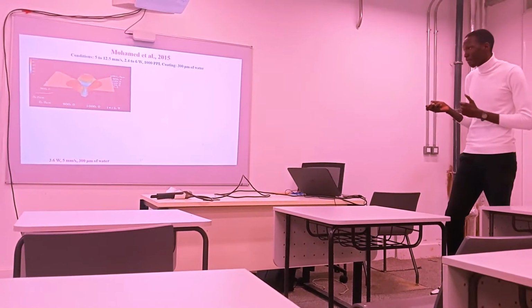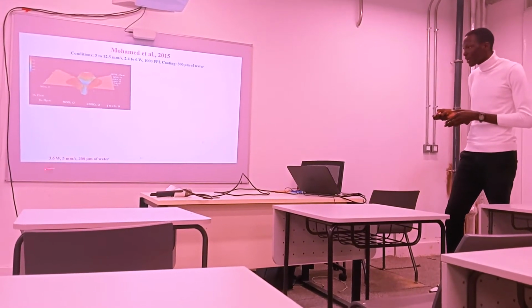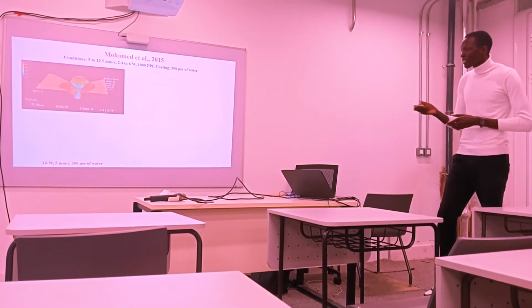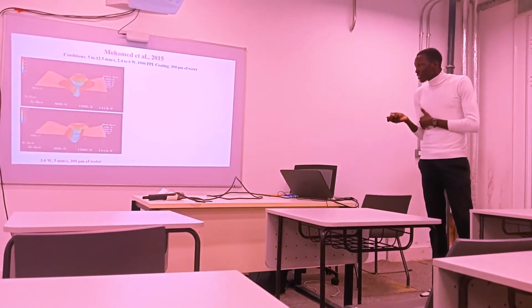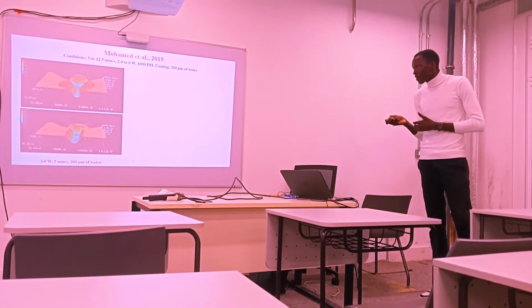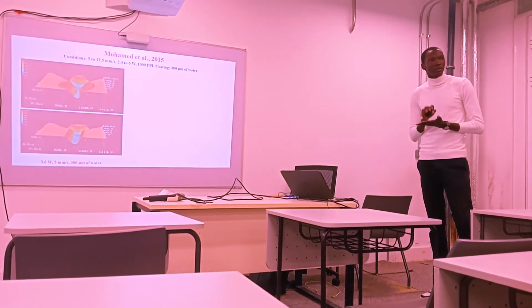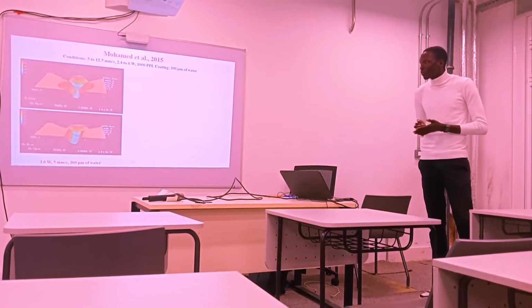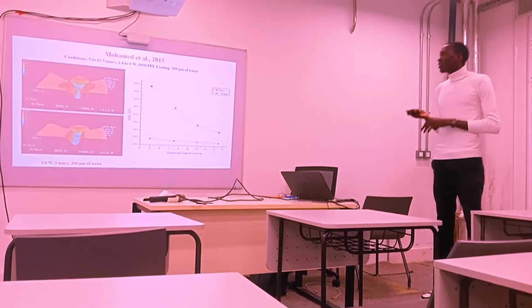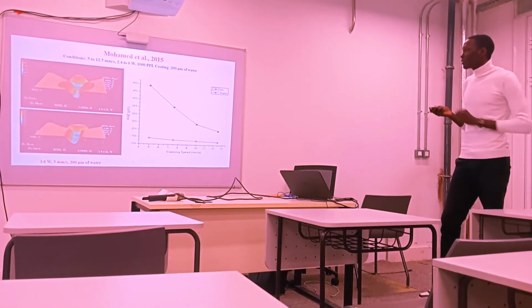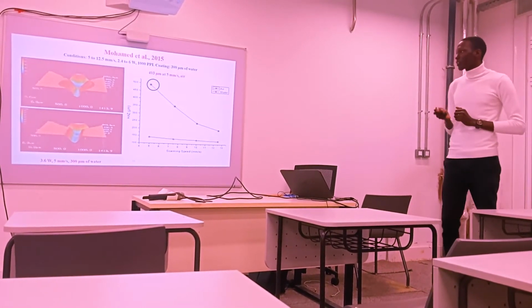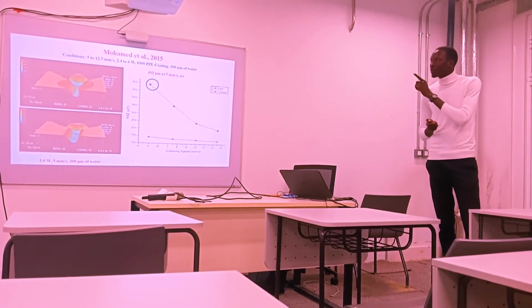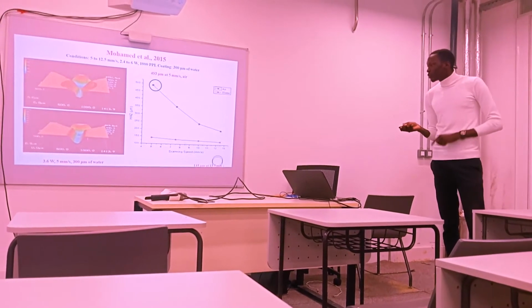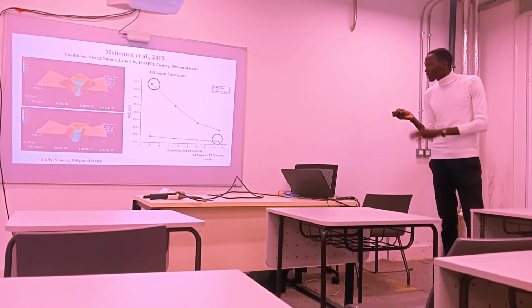This is in air at 3.6 watts, 5 millimeters per second. Now, this is what they found in water when they coated the material with water before fabrication of the microchannel. They were able to reduce the heat-affected zone from 493 micrometers in air to 142 micrometers underwater.